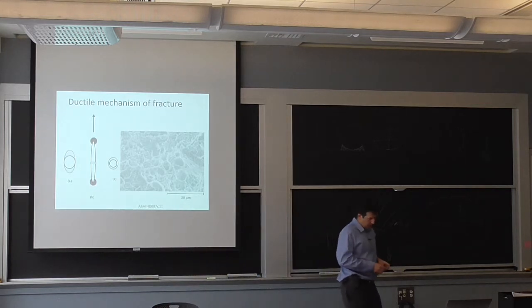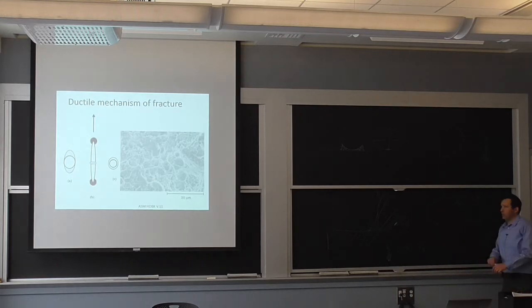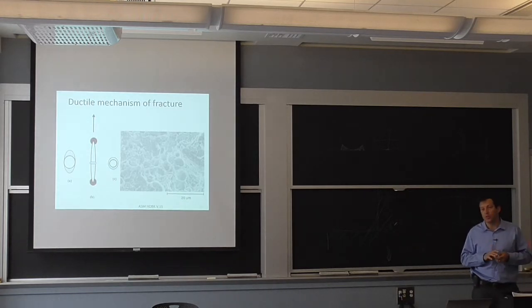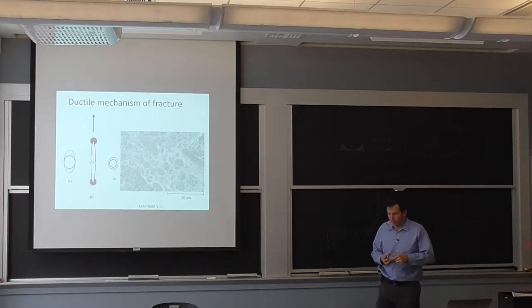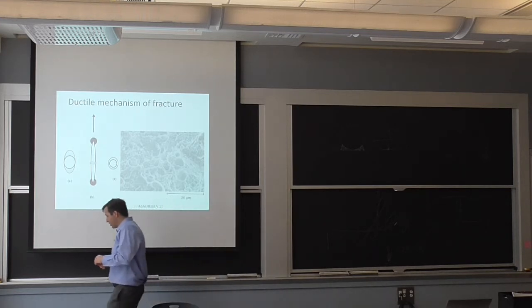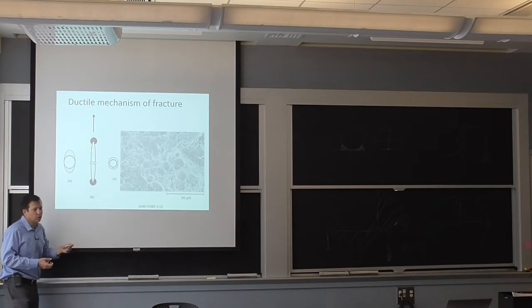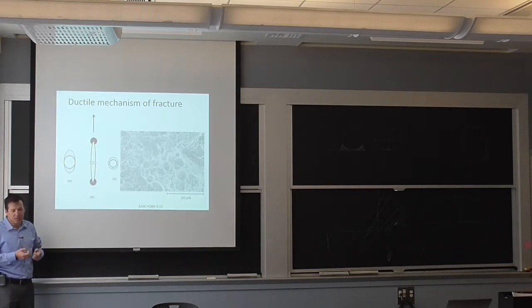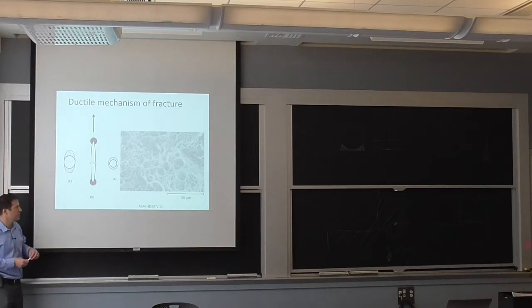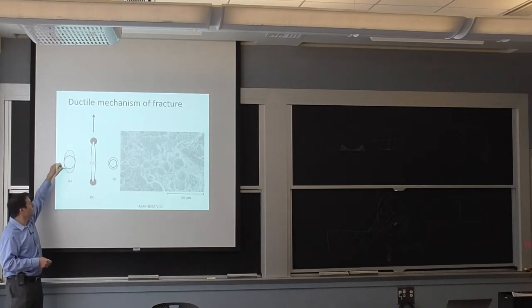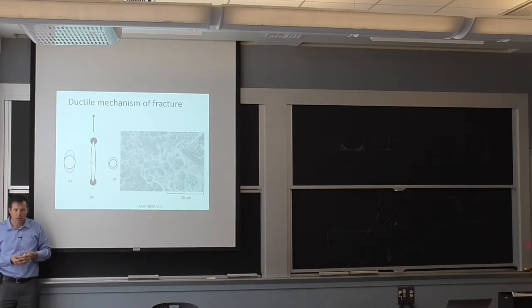What happened is you deform at the tip of the crack — let's put a number, say 70%, 100%, something of that order. It's not the 20% that you get in the lab if you're doing a tensile test — it's a lot more. At a certain point, the same way that you would start creating a void if you have a little particle in the material — there's always something sub-microscopic, it could be the grain boundaries, it could be an inclusion — that essentially allows for a debonded interface to create, and now we're starting to have microvoids.